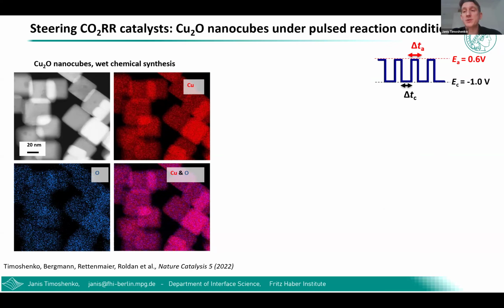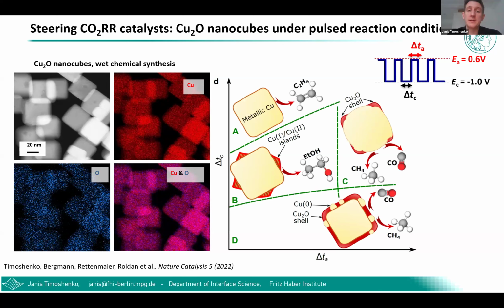And now, by just tuning the knobs on your potentiostat or just changing the duration of applied potential pulses, we can actually steer the catalyst into different regimes, where we can have a completely metallic or nearly completely metallic catalyst, one which has thick oxide shells, or one with some nice islands of oxide with peculiar oxidation states. And each of these different regimes has different catalytic properties, resulting in different reaction products, starting from the same CO2 molecule.